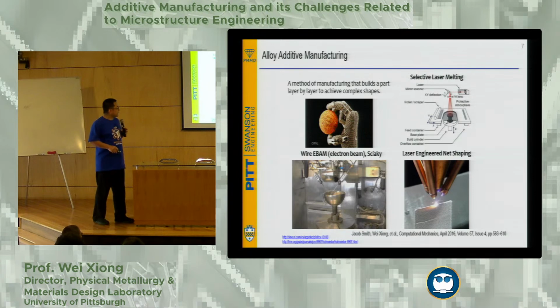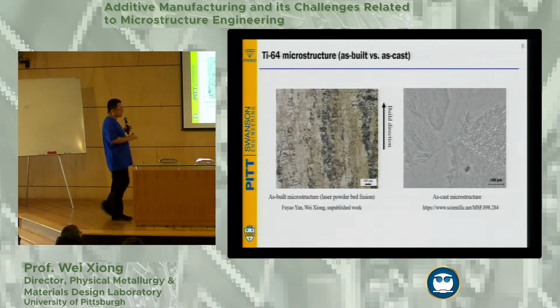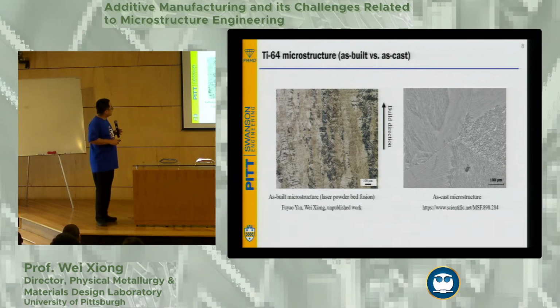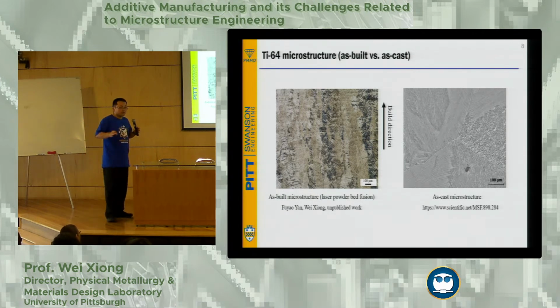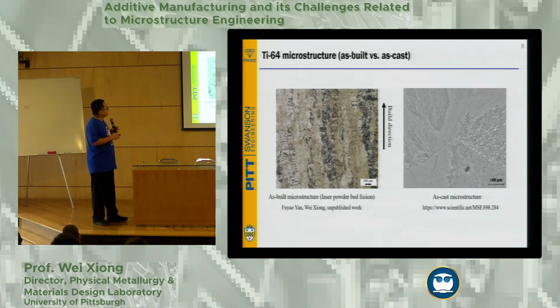Okay, so we're talking about microstructure in this lecture. What is the difference? If you check some printed microstructures of Ti-6-4, which is very commonly used among Ti alloys—the left-hand side is the as-printed microstructure from the laser powder bed fusion process, and that's the building direction. You can see columnar structures start to show up, versus the as-cast microstructure from casting foundry, which doesn't necessarily have a strong texture like this.